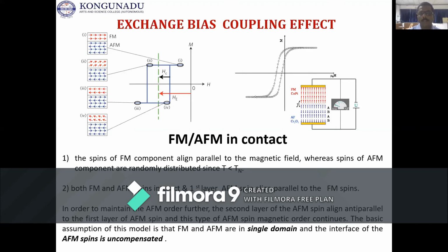This magnetic effect you can observe through a shift in the magnetic hysteresis loop from its symmetry point. You can see in the animation the magnetic hysteresis loop shifting towards the left. That is a negative exchange bias coupling, usually observed in magnetic memory devices, where you can also have a positive exchange bias effect, a vertical shift. Many types of structures are used, and depending on them, the magnetic shift will be seen. When you have a shift in the magnetic hysteresis loop, you can say that you have a strong magnetic device where you can store a large amount of data.